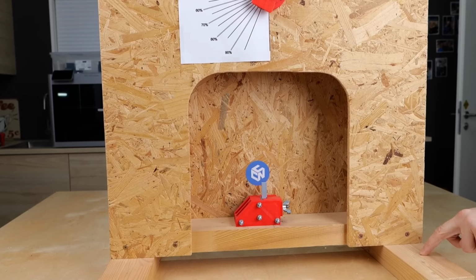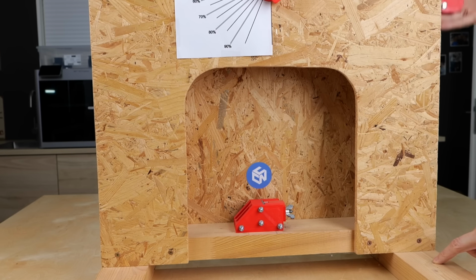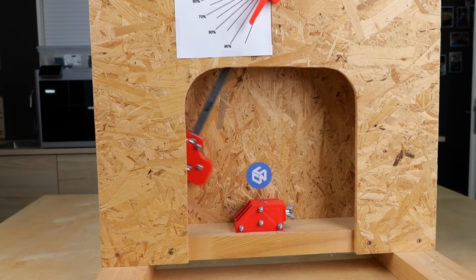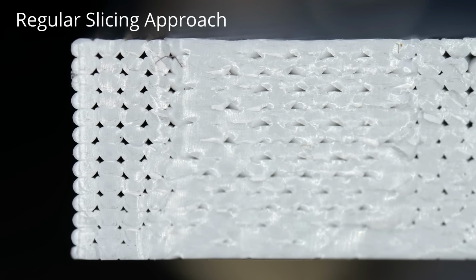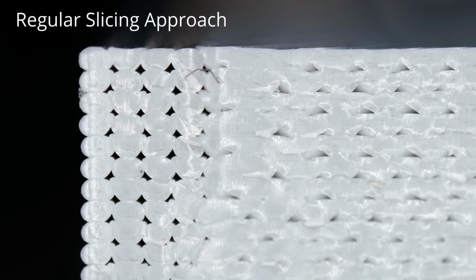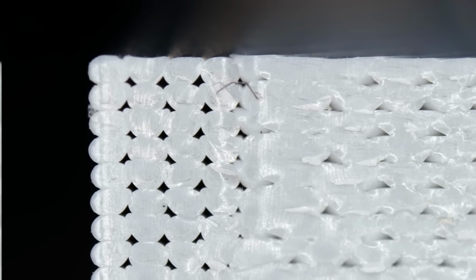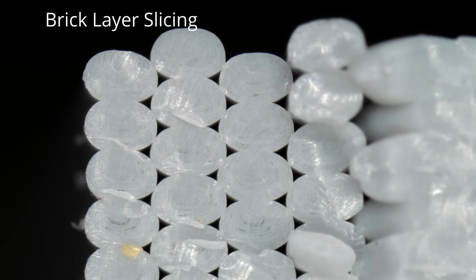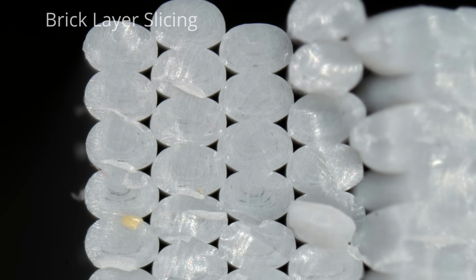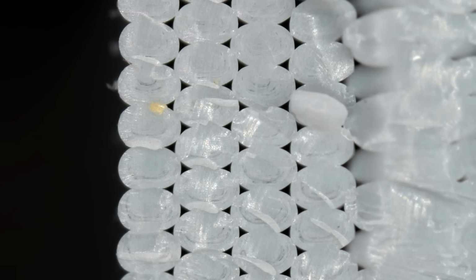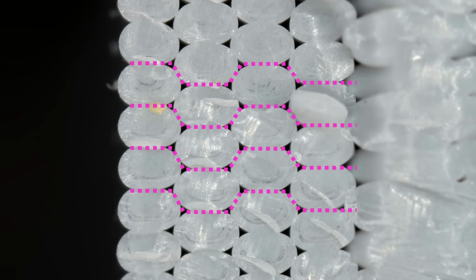I broke some of the parts to get an idea of how much the slicer preview correlates with the real part. Looking at them under a microscope shows how the perimeters align when using conventional slicing. The brick layers, on the other hand, end up with a really nice interlocking pattern, where the individual extrusions not only touch at the bottom, but also diagonally to the next layer.